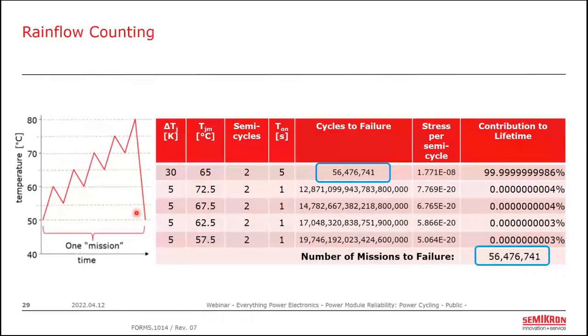Also, this particular example too, because of the values we've chosen here, also really reinforces how those tiny delta T's of 5 Kelvin have an insignificant impact on life with the new model. You know, we have a comically large amount of cycles to failure and a very small contribution to this. But you can imagine if these were larger delta T's that you might have a different distribution here.